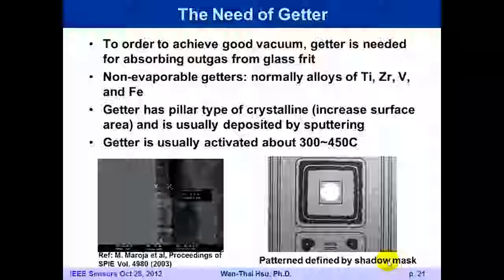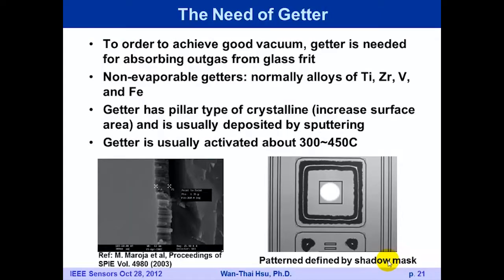When we initially developed this process, we used 4-inch wafers. We have a 4-inch screen, which is basically metal. And you see the thermal expansion is different. Once you mount them together, and once you have the sputter, the temperature sometimes gets high, and as the process goes on, you start seeing these dots kind of move to the outside of the wafer.